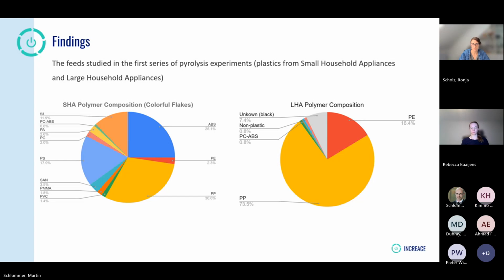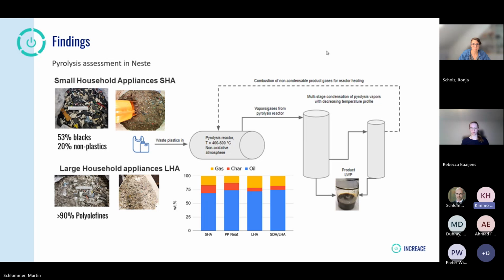And next slide. It tells about the first results, the columns in the middle, so the oil yield was around 70%. We also had neat polypropylene there as a reference, which actually produced 75% of oil. That also produced char in that process, a little bit surprisingly high amount. But the pyrolysis as such was done at about 500 degrees in a non-oxidative atmosphere under nitrogen, and then the vapors from the reactor condensed in a two-step condensation, and then actually they were combined into one liquid product.